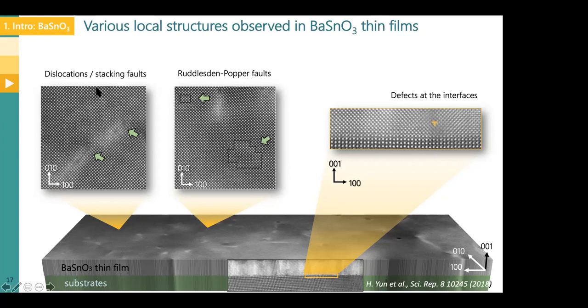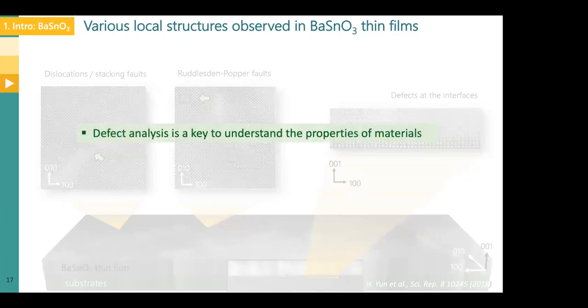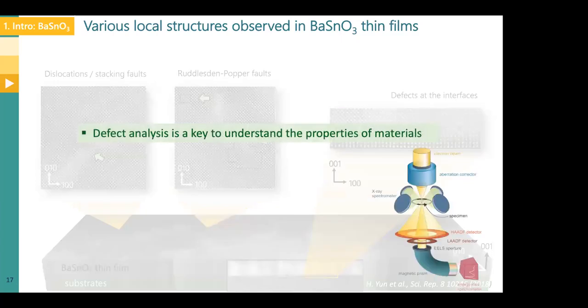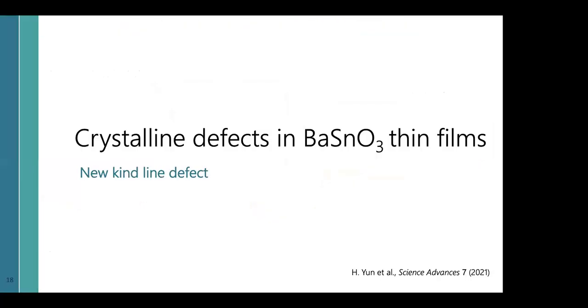What you can see, I'm hoping you can see, is that sections of the crystal look nice and perfect, but there are places with defects, marked with these green arrows. Sometimes they look like a spot, sometimes they look like planes. They are there, which is good news, in the sense that the material has defects, and we should look carefully at what's going on there. So we have our microscopes, we have everything in place. Now we're going to look at the defects, to see if we can identify the type of defect that we are after.